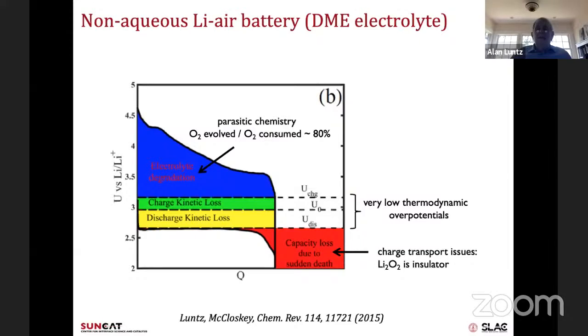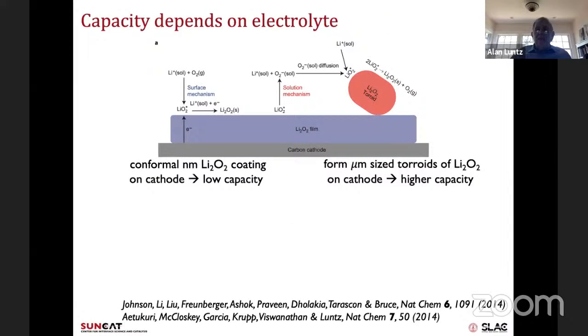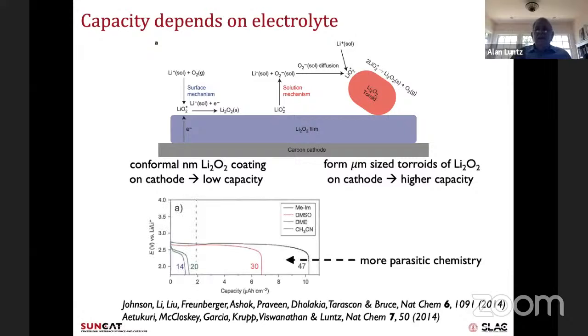These are problems that haven't been solved yet. You can get the capacity higher by changing the reaction mechanism, but you also get more of this parasitic chemistry. So right now it can give reasonably high capacities, but it doesn't have a good cycle life, and no one has actually solved that problem. There are lots of efforts to try to solve this issue using things called redox mediators, where you change the mechanism of the reaction a little bit and so forth, but none have been terribly successful.